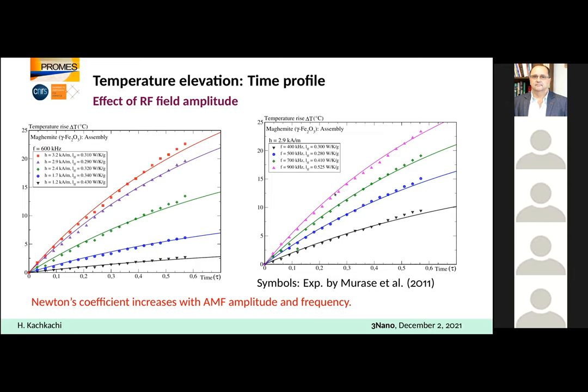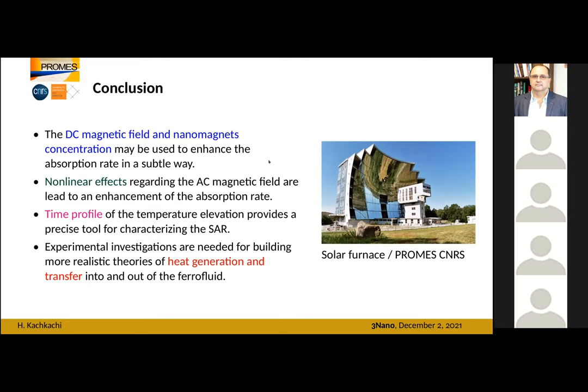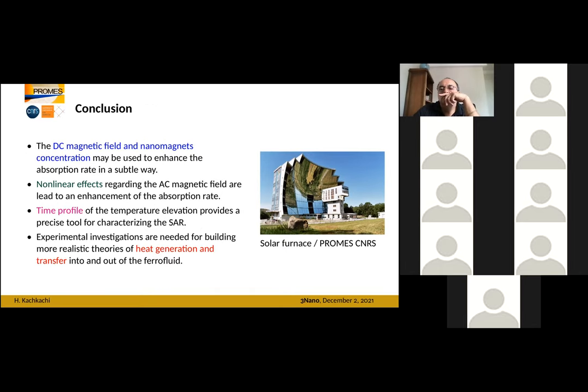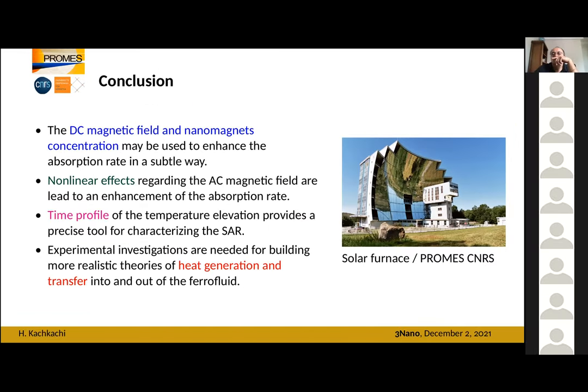This is my conclusion. I hope I convinced you that there is a subtle play between the DC field and the concentration in the optimization of the SAR. So it's not straightforward. You can't just increase the DC field or the concentration to enhance the SAR. Nonlinear effects also contribute to some extent, because, I didn't say it, but our calculations are based on perturbation theory, so it's not an exact calculation. But it does show that this physiological limit has to be revisited with regard to nonlinear effects.